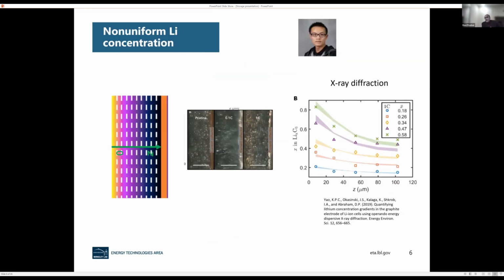So one other thing we recently did was we started looking at what happens when you fast charge. First of all, as I mentioned earlier, the extreme case is plating, but even with moderate fast charging, you can start seeing non-uniform diffusion of lithium inside the anode, okay? So let's say here is the anode and the lithium is going in, right? As a function of the Z direction, the thickness, you should see that the lithium is not uniformly deposited. And 1C charging means that you're charging the battery in 1 hour. 0.1C means that you're charging the battery in 10 hours, okay? Just look at it that way. It's inversely proportional to the charging time.